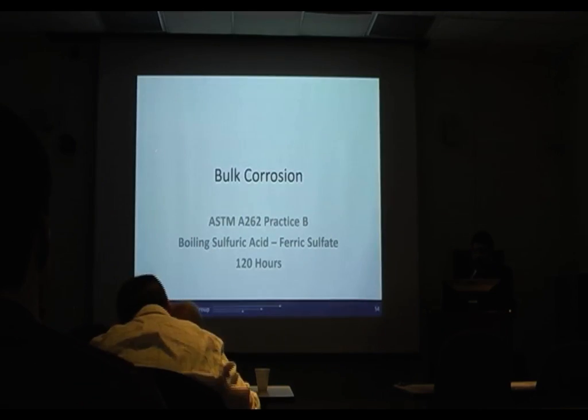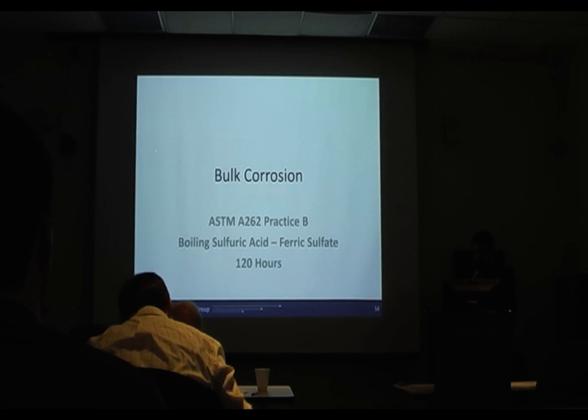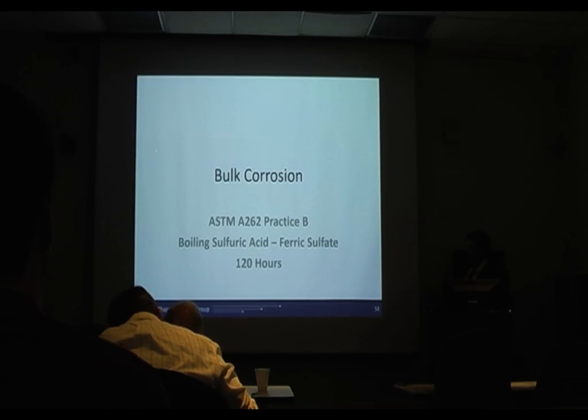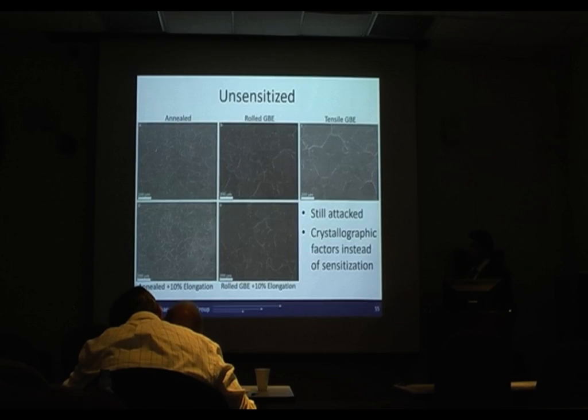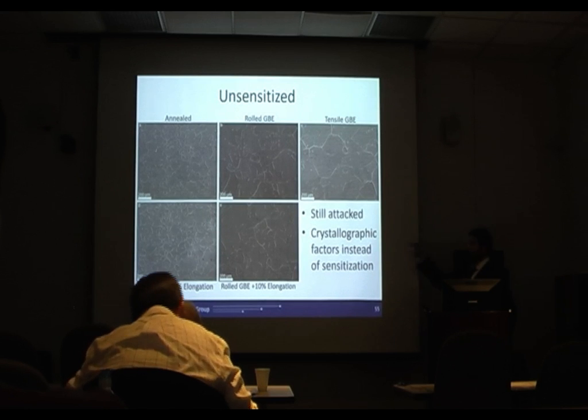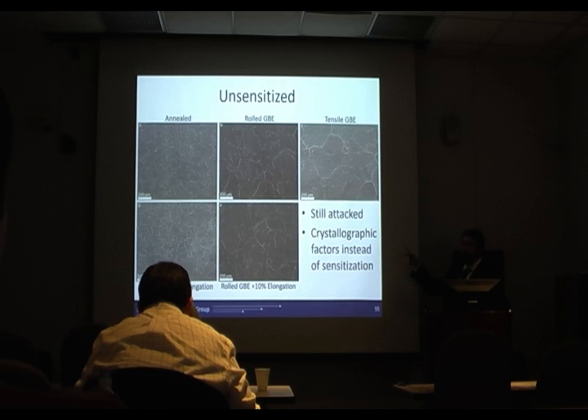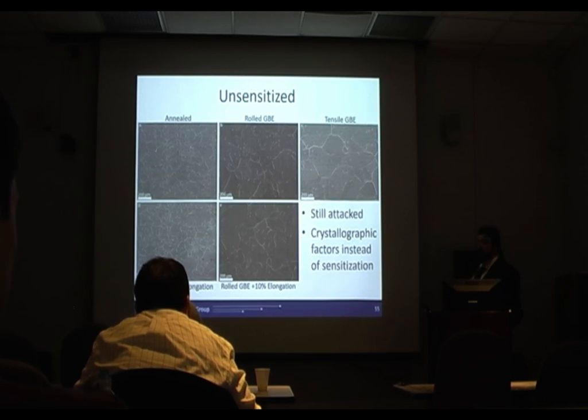Moving on to the bulk corrosion, we have the 262 practice B. The standard method involves immersion for 120 hours and massing the sample before and after to see how much mass it lost. And when we look at our unsensitized samples, so these were all quenched, but they were not heated into the sensitization range again, you can see that we are getting attack at the grain boundaries, indicating just how aggressive this environment is.